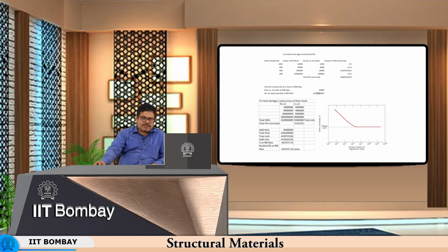33.7% is available, and so what I do is that I have this 40,000 at 900 MPa. So, of these, 33.7% is available, and therefore, I get 13,467 cycles which are available at 900 MPa. So, now this is based on Miner's rule. Based on Miner's rule, the fraction of the total fatigue life for a fresh sample or a fresh product at 900 MPa has been given as 40,000 cycles, and given just the 33% life that is available, because already the fraction of life consumed is 66.3%, then what I can possibly get is very safely get.